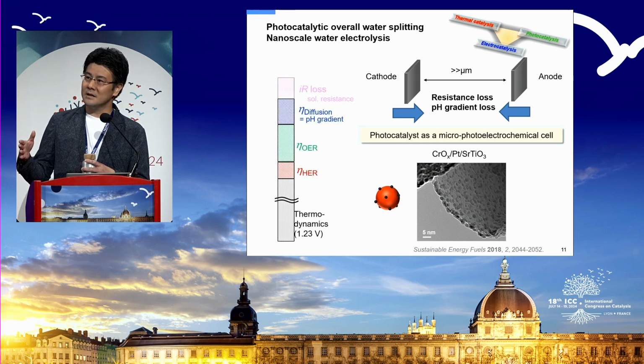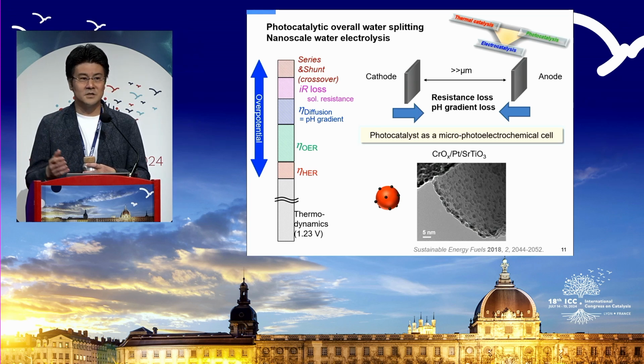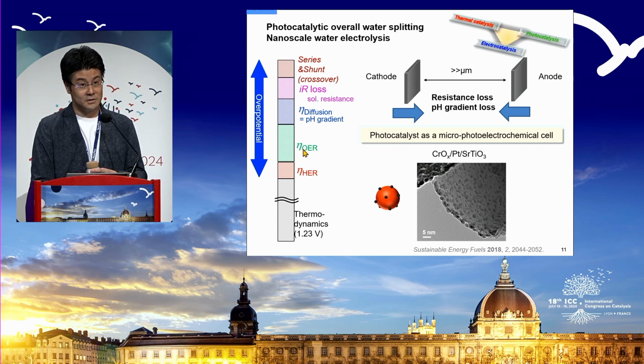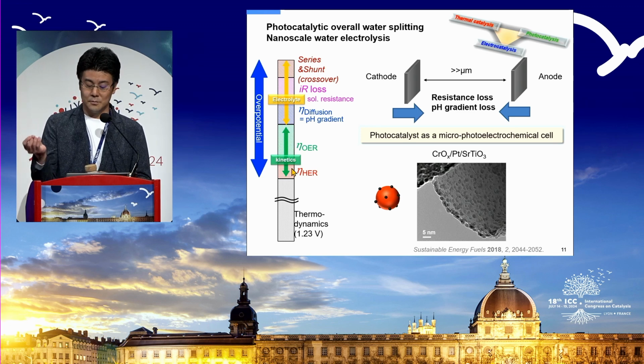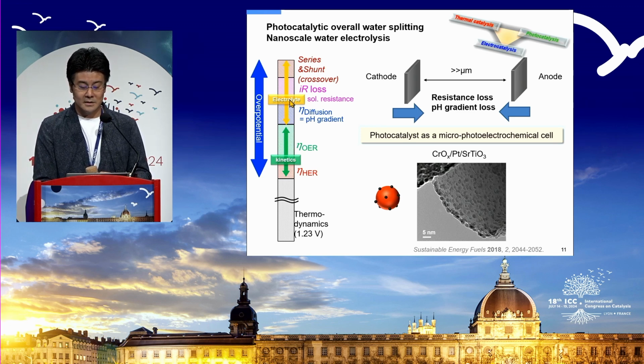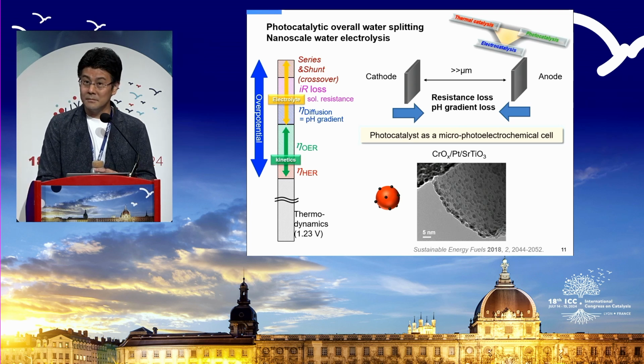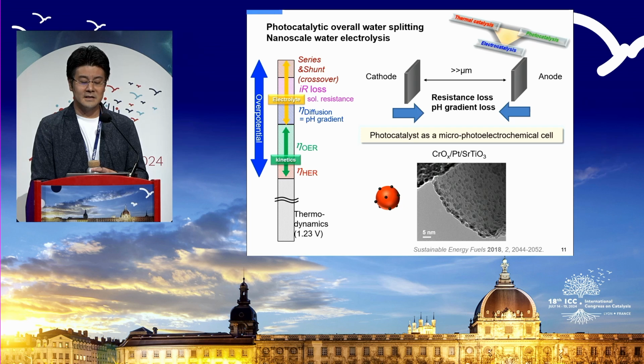So if you translate that into water electrolysis terms, what is overpotential coming from? It's hydrogen evolution kinetic overpotential and oxygen evolution kinetic overpotential. Then it comes to the solution side, where you have a pH gradient and solution resistance. And then you may have a crossover of the gases that may be an additional loss. Here, this is the electrode, or in this case, the co-catalyst that you're putting. But the additional part in yellow is coming from the electrolyte, and that has nothing to do with the photocatalyst material. You can separately quantify the contribution of the overpotential coming from the solution.